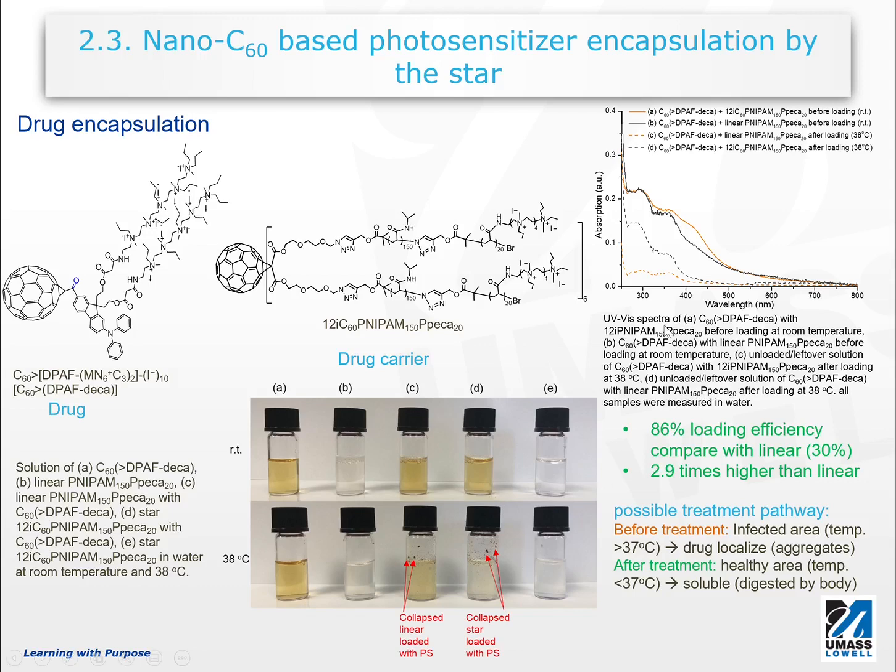visualize it. And we also did the calculation based on those data points, and we find out that our star polymer has about 86% loading efficiency, comparing with the linear polymer, which only has about 30% loading efficiency. Comparing these two, the star polymer has almost 3 times higher loading efficiency than the linear polymer.